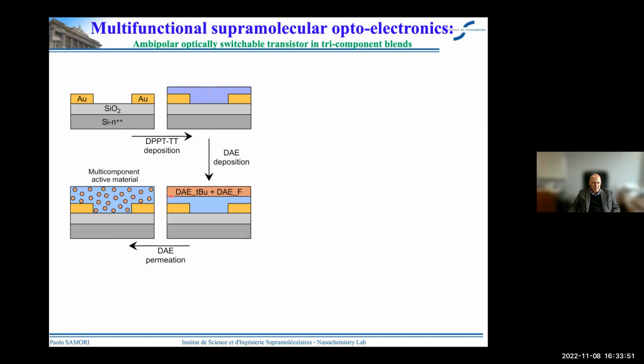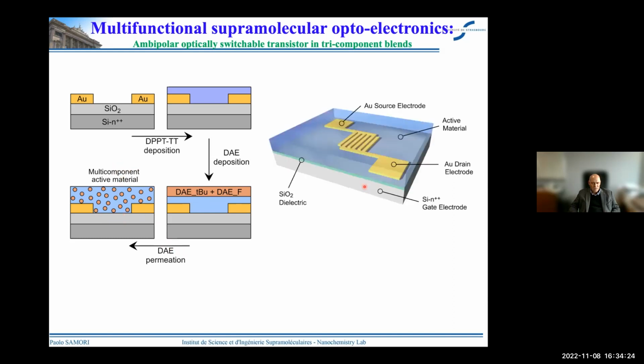Then we deposit a thin layer of diarylethene blend on the top of it, with the two different diarylethenes, one that is tailored to trap and untrap the electron transport, another for the hole transport. And then we applied a mild temperature of about 80 to 100 degrees to trigger a permeation of the diarylethene from the very top through the layer of the organic semiconductor that is about 100 nanometers thick. And actually, we are certain that it reaches the interface with the dielectric. Of course, we use bottom gate, bottom contact dielectric,